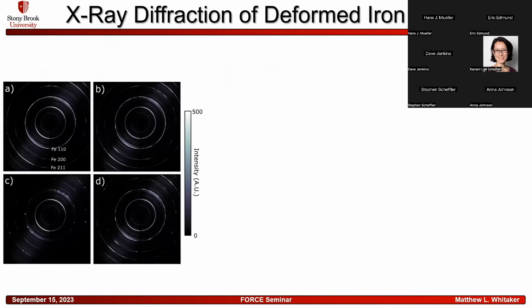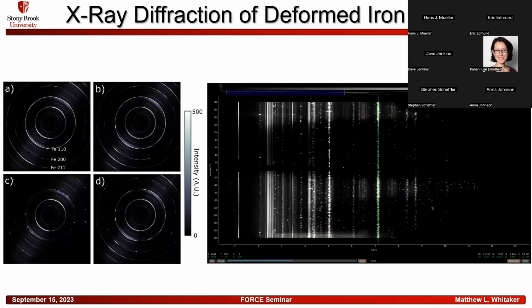So to show it a little bit clearer, what I'm going to do is take the X-ray diffraction images that we see at the left, and we're going to do what's called a cake plot, which basically you slice the diffraction pattern around, much like a cake, around its center, and you unfold it. And what will happen is when you have a perfect circle on this diffraction pattern, it will become a straight line in the cake plot.